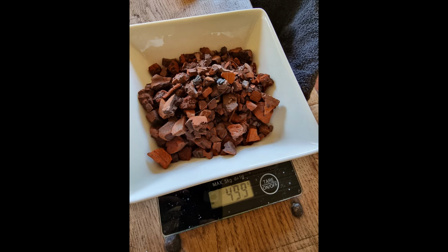Furthermore, the trace elements found in this type of iron ore match perfectly with the chemical analysis of our sword under investigation. We find cobalt, copper, zinc, nickel, arsenic, but also titanium, chromium and vanadium, and small amounts of molybdenum in this ore as well, giving it a 100% match in the trace elements of the Ulfbert sword.